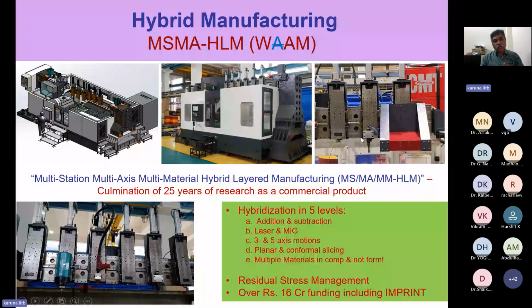You know, when you do welding and produce the layer, a lot of stresses get built because of the thermal gradient. So the nature of the stress is tensile. So when you hammer on the welded surface, you nullify the tensile stress and then it becomes a normal component. Sometimes if you want more strength, you can hammer more and make it compressive instead of tensile. So then you can produce a forging-like component. So this is a kind of stress relieving system.